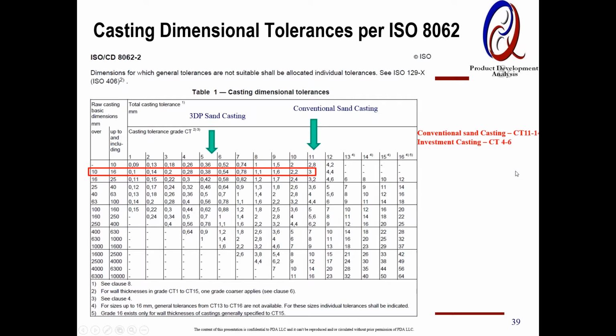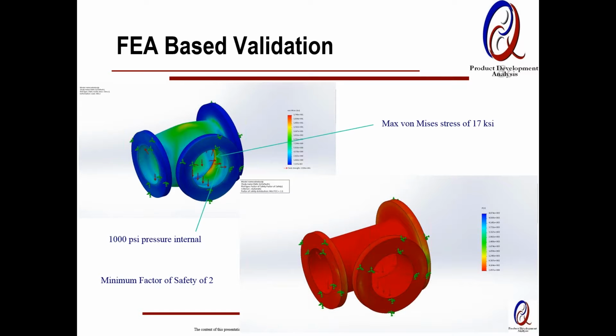This is, by the way, this table is a function of the processes and the basic dimensions. So if you look at here, conventional sand castings, it's anywhere from here to here. The investment casting would give you the tolerances spread 4 to 6. And based on our limited experience, the 3D printed sand gives us pretty close to the investment casting. So say, for example, instead of picking CT11, if you pick CT5, look at the variability on a key dimension. It's plus or minus 3 versus plus or minus 0.38.